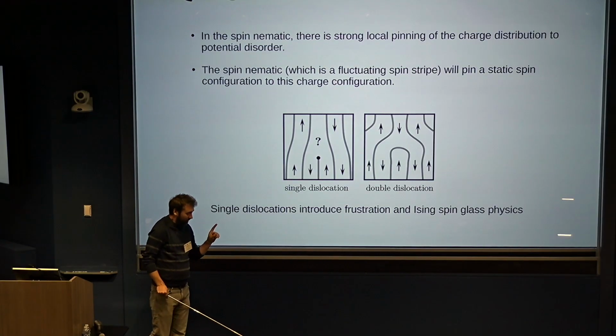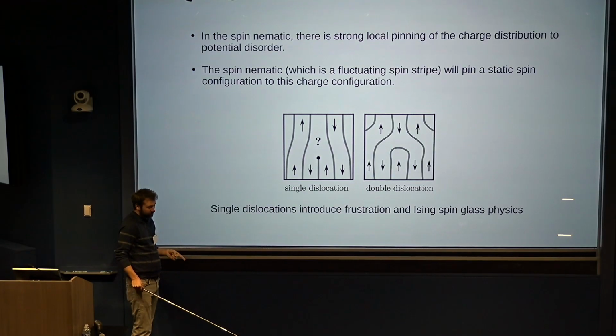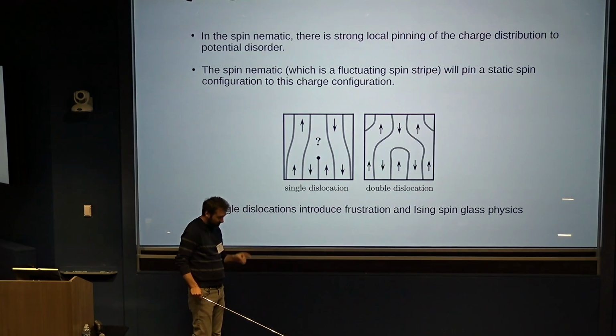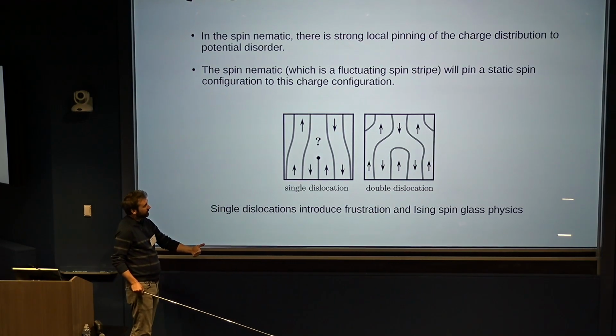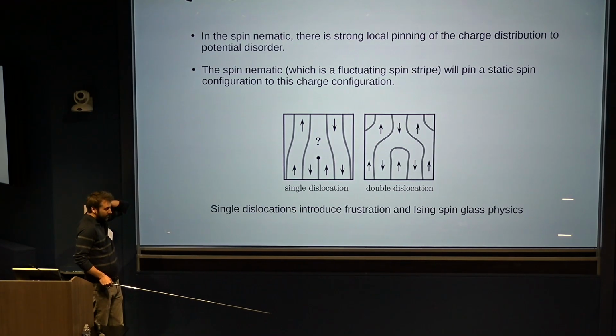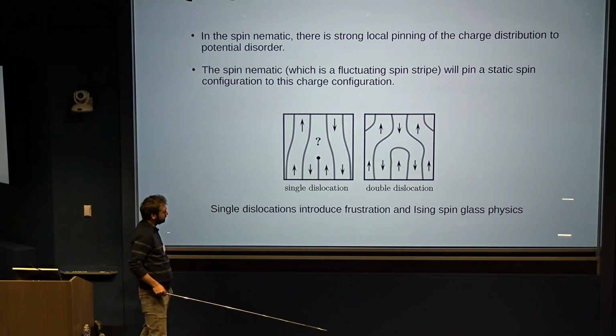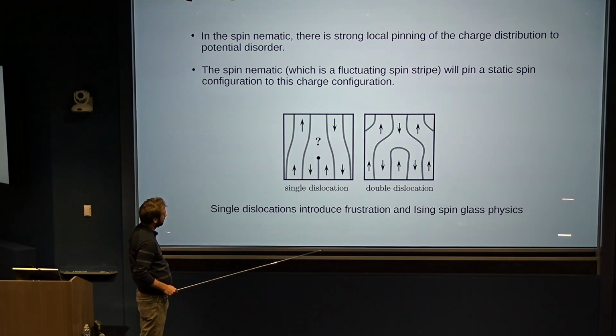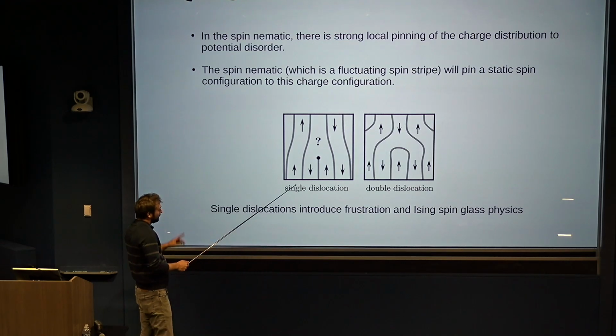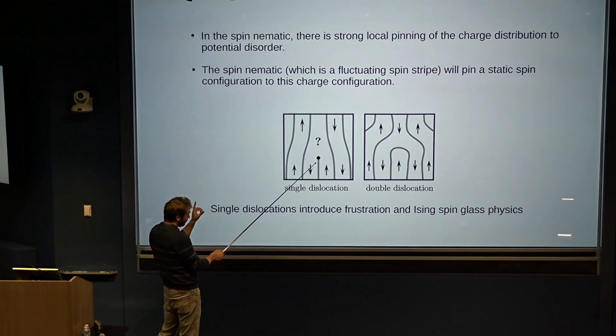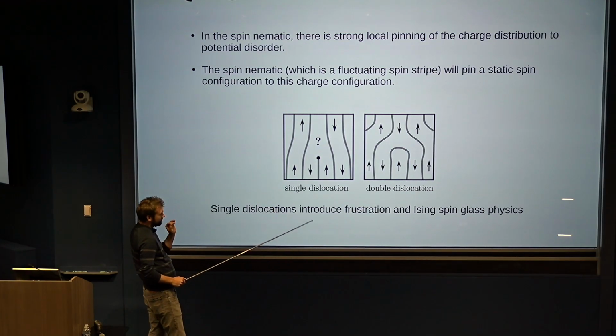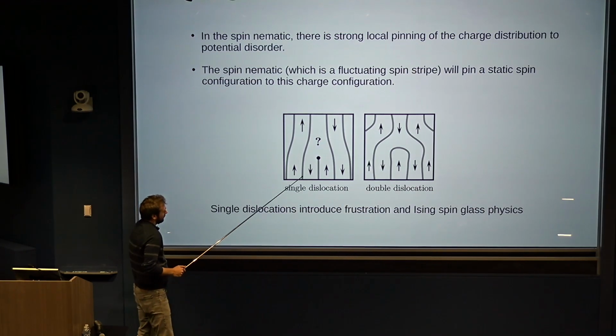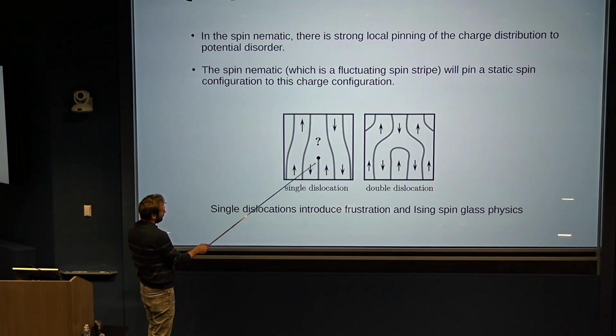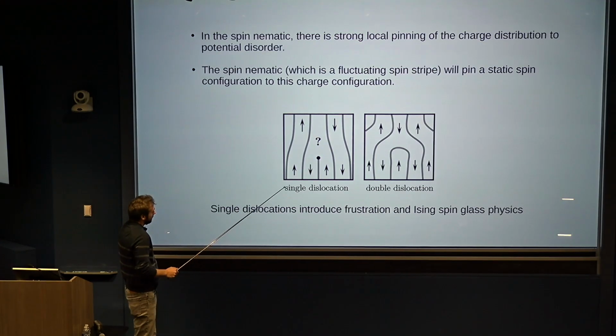So really, what made the magnetism go away was charge fluctuations. So if you quench the charge fluctuations with a random potential, the magnetism should also come back. And that's really what happens, if the disorder is not too small, at least. One important caveat is that charge disorder, definitely short-range charge disorder, actually induces frustration for spin order. The reason is that in a random configuration, you can have these dislocations, where one of these gray lines just ends. This is a dislocation in the charge density wave order. So then the spins are frustrated.